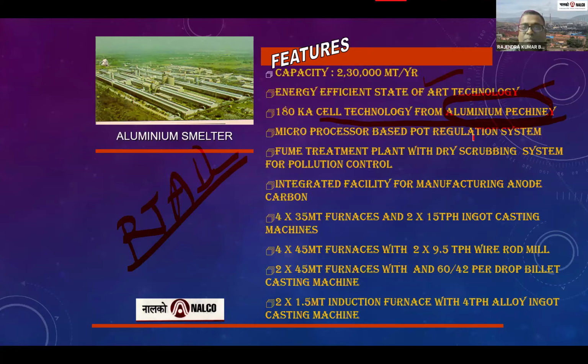Microprocessor based pot regulation system, fume treatment plant with dry scrubbing system, integrated facility for manufacturing anode carbon, 4 into 35 metric ton furnaces and 2 into 15 TPH ingot casting machines, 4 into 45 ton furnaces with 2 into 9.5 TPH wire rod mill, 2 numbers of 45 metric ton furnaces and 60/42 drop billet casting machine, two numbers of 1.5 induction furnace with 4 TPH alloy ingot casting machine. In the smelter plant, it's available.